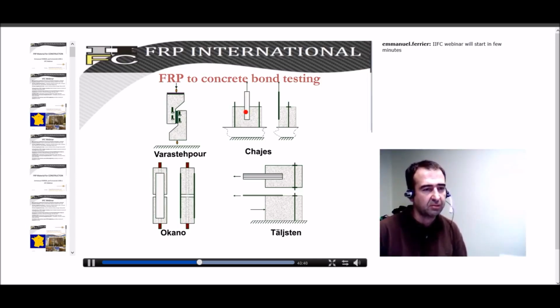We have the single lap shear test. It's quite commonly used. In certain cases it is quite difficult to apply because you can have some flexural behavior, and the mechanical properties are quite difficult to obtain. Then Täljsten, for example, developed such a single lap shear test. The sample is connected to a block, and then here a compressive force is applied and a tensile one here, so that shear will develop in the interface.